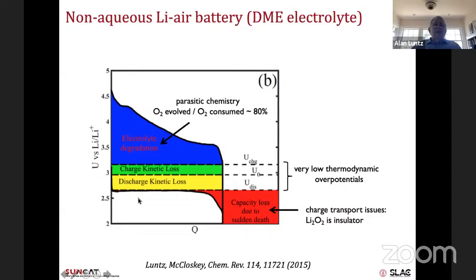it works. The electrochemistry is very good. You have very low overpotentials, but it dies very quickly when you try to discharge it. And that's because this material that you're making is an insulator. So it passivates the electrode. So you can't live with that. And the other problem is when you